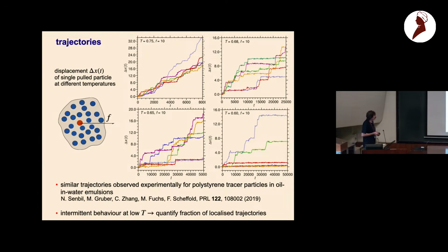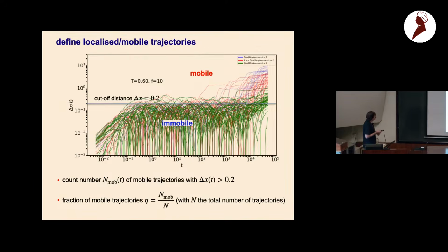Now we can quantify the fraction of these localized trajectories. One way of doing this: here is the displacement as a function of time, and we can introduce a cutoff, saying all that is below the cutoff is immobile and all above is mobile. Then we can determine the fraction of trajectories, denoted by eta, that are mobile.